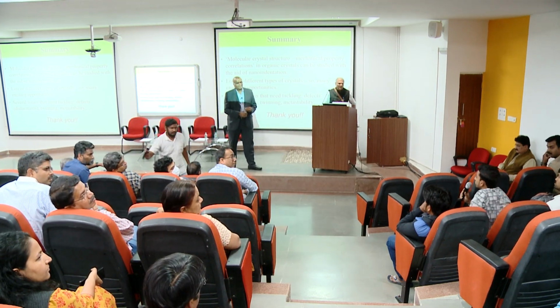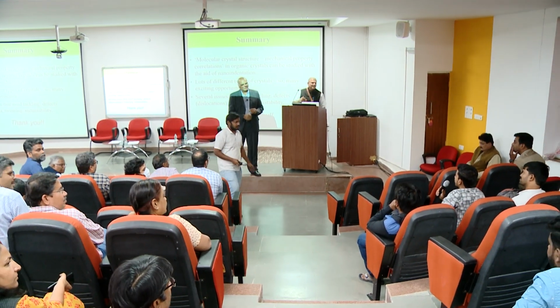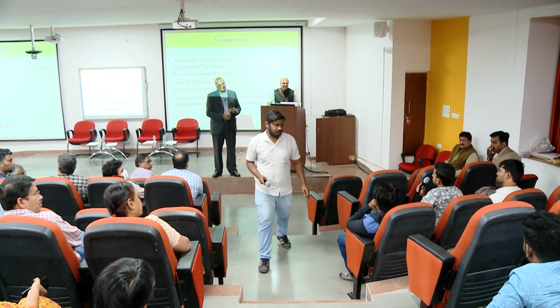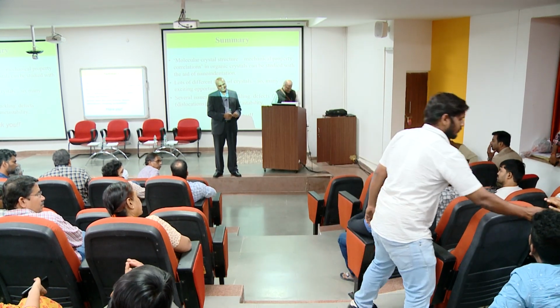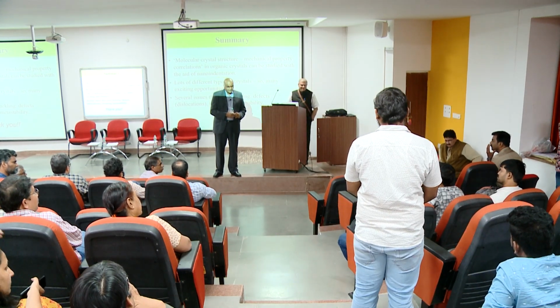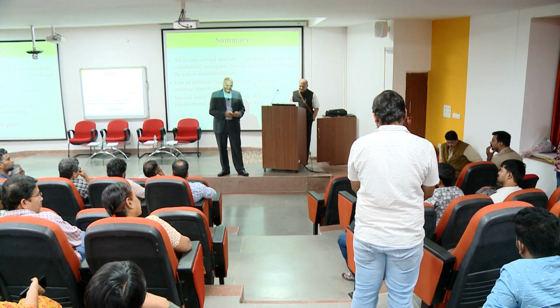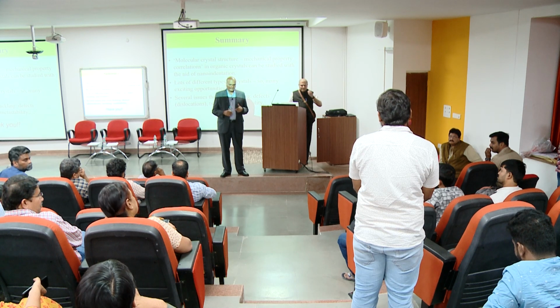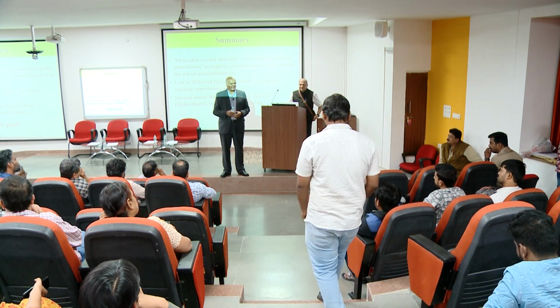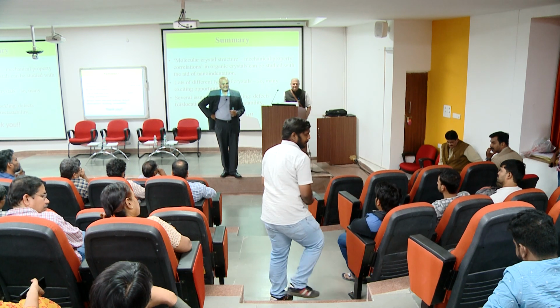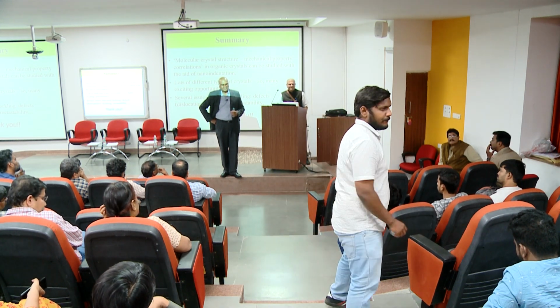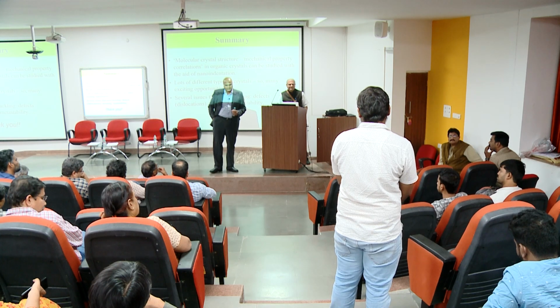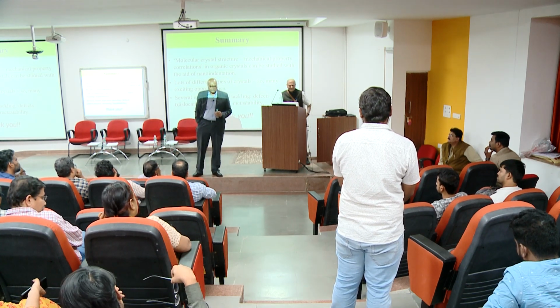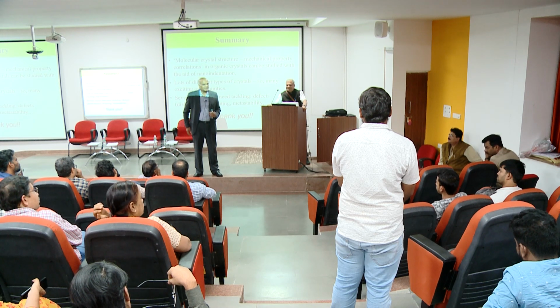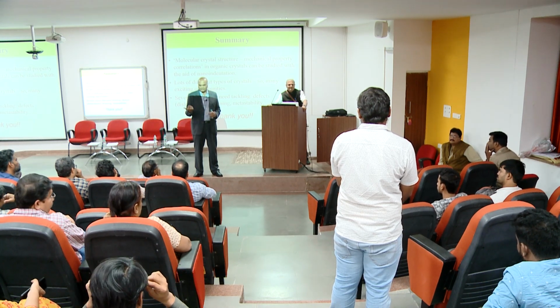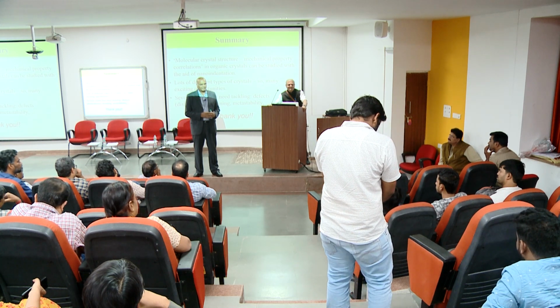You always talk about single crystals, but during nano indentation, do you feel that there is some indentation creep? Creep will occur, especially in these cases, because the weak interactions can break and reform with time. So there will be rate dependency and time dependency. We have looked at some rate dependency, but not really the creep effects. I think people have started looking at it. Yesterday or today I saw a paper looking at creep characteristics.